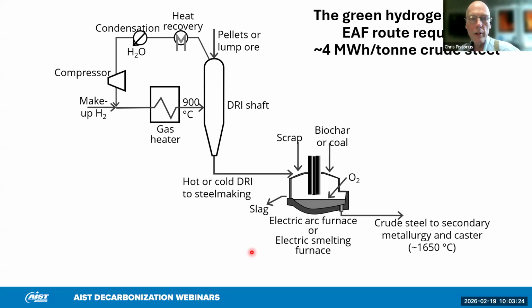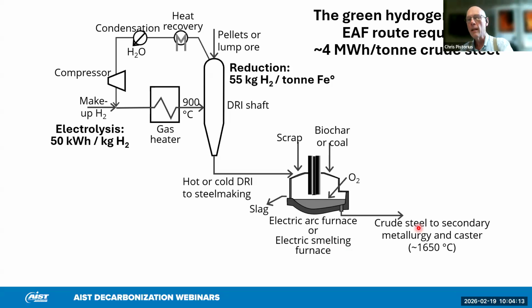So here is one such instance. This is very roughly the HYBRIT or Stegra type process, where we use hydrogen to make DRI, which is then ideally transferred hot to an electric arc furnace, or if it's higher gangue material, an electric smelter furnace, to make crude steel. And the numbers, as I show in the top right, add up to around 4 megawatt hours per ton of crude steel. Where those numbers come from is what you need to produce the hydrogen. I have a slightly more optimistic number than Sarah's, but it's somewhere around 50 to 60 kilowatt hours per kilogram of hydrogen. Of course, we need stoichiometrically around 55 kilograms of hydrogen per ton. So if you multiply those two numbers, you're already over 2.5 megawatt hours per ton.